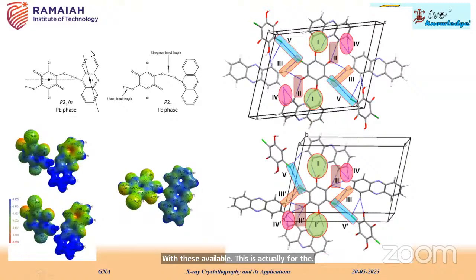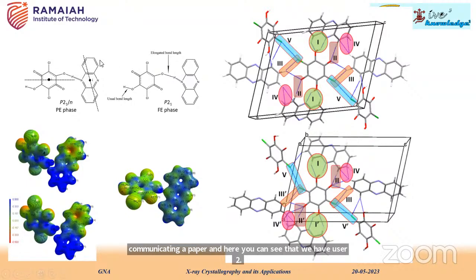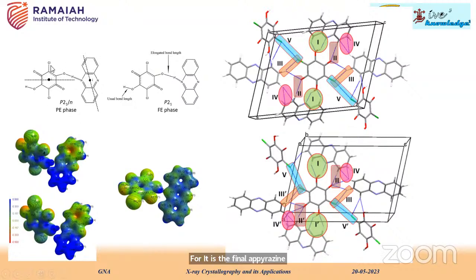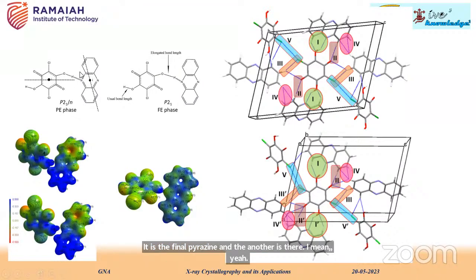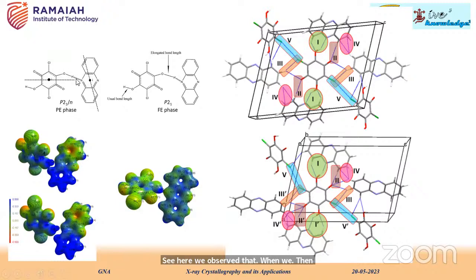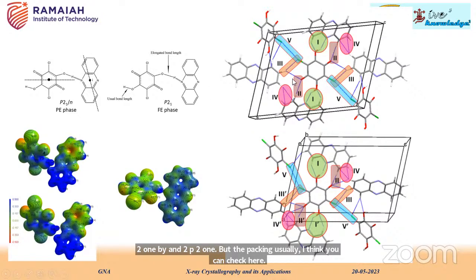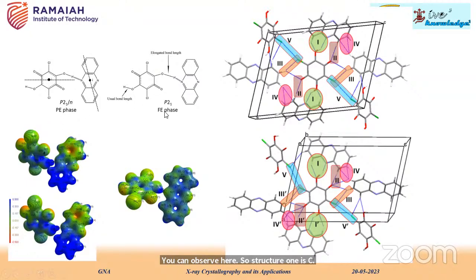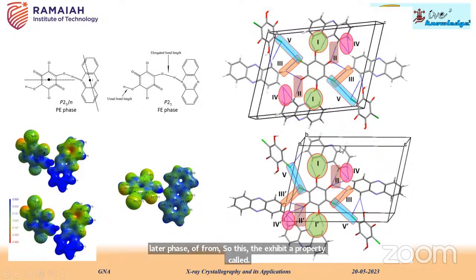We are recently communicating a paper, and here you can see that we have used two co-crystals. One is pyrazine, and the other has a 2-chloro benzene ring here. We observe that when we use different temperature conditions, the structure of the material changes from P21/n to P21. Both are monoclinic, but the packing is different. You can observe here that structure one is the PE phase, the paraelectric phase. It transfers from paraelectric to ferroelectric. So this exhibits a phase called paraelectric, whereas this exhibits a phase called ferroelectric.